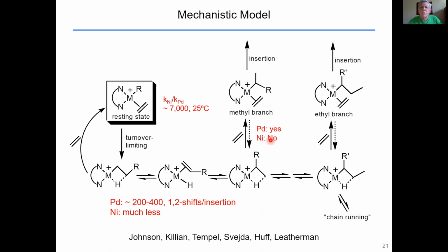Now, in the case of nickel, once this agostic species is trapped by ethylene, it's irreversible. So as you increase the ethylene pressure, this species gets trapped earlier and earlier in this chain running process. And so at high ethylene pressures, you basically sit here and generate almost linear polyethylene. As you lower the pressure, you see increasing methyl branches. And as you lower the pressure further, you can see ethyl branches and longer branches.